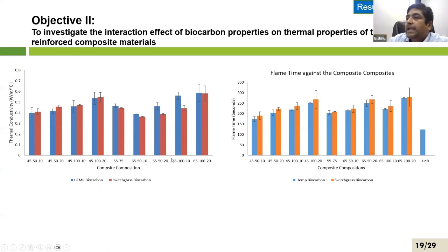So by adding 20%, even 10%, the thermal conductivity was going down. So it was showing that it can further reduce the thermal conductivity of the composite material. Flame time against the composite: it just shows how long it takes for the flame to be self-sustained when it is exposed to 10 seconds of fire.